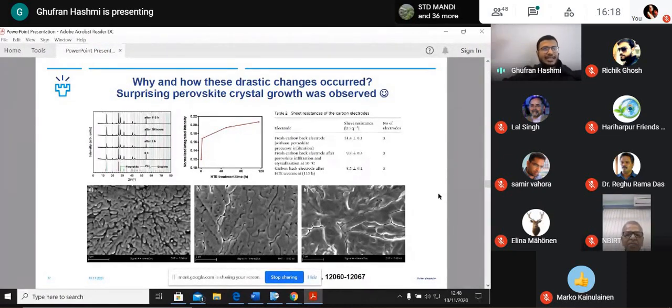So then it allows steam to go through and kind of kiss the perovskite crystals. And what happens? From the outer boundary, before fully degrading, they start fusing together with a neighboring crystal. And that's why they were turning into large crystals.